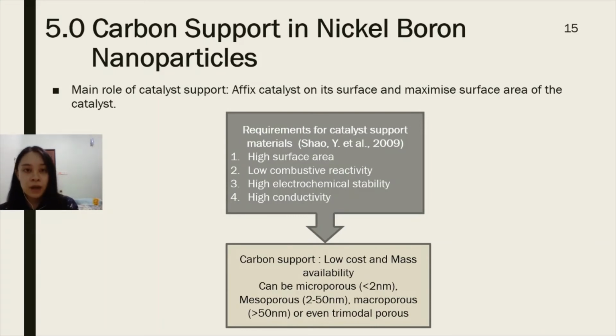So the role of catalyst support is to fix the catalyst onto the catalyst support surface in order to maximize the surface area of the catalyst. Some of the requirements for catalyst support includes high surface area, low combustive reactivity, high electrochemical stability, and also high conductivity. So these carbon support actually all fulfill these requirements, and also it is available in low cost and has mass availability. Also, it also has a presence of different porosity, which includes microporous, mesoporous, macroporous, or even trimodal porous.